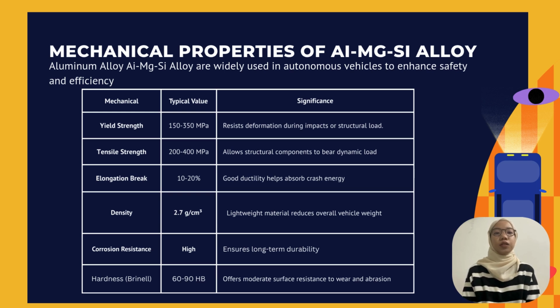Meanwhile, the Young's modulus is about 69 gigapascals, so it's stiff enough for structural use, but not too brittle. Its hardness is between 60 to 90, offering decent protection against wear and abrasion. Plus, it's quite lightweight with a density of just 2.7 grams per cubic centimeter, which helps reduce the weight of vehicles and boost efficiency. Lastly, it has high corrosion resistance, meaning it lasts longer, even in harsh environments.